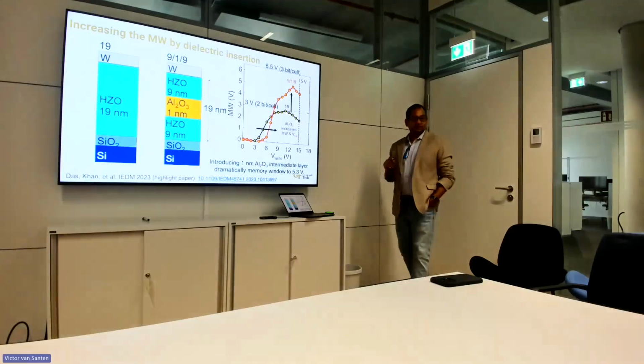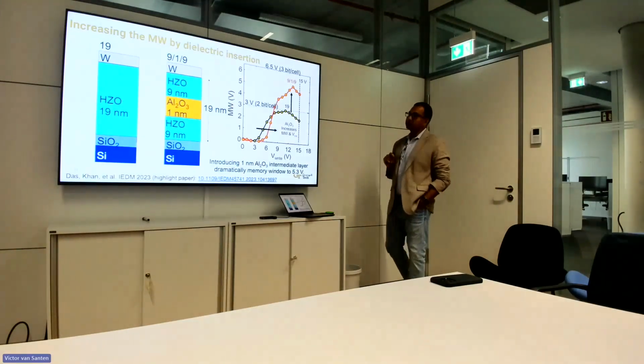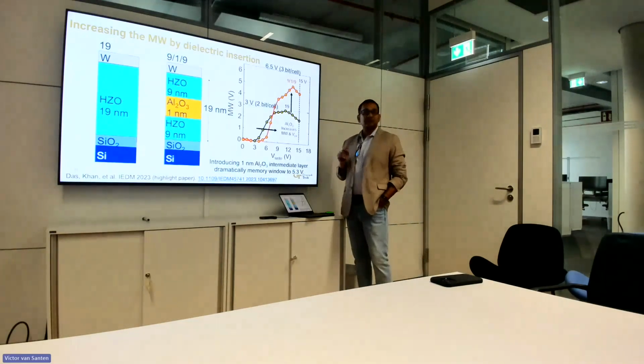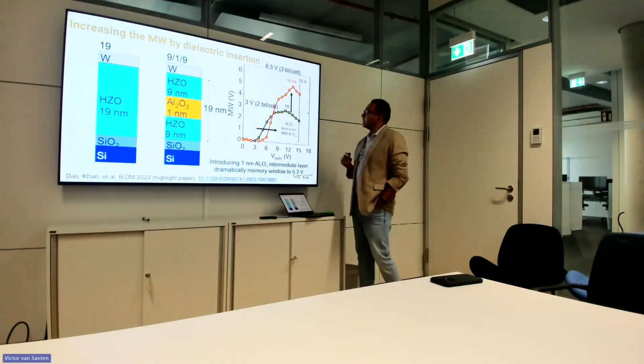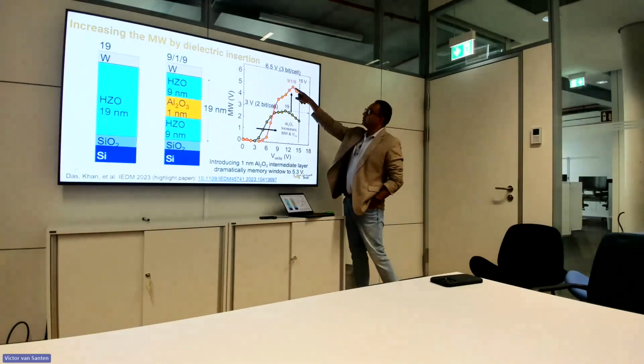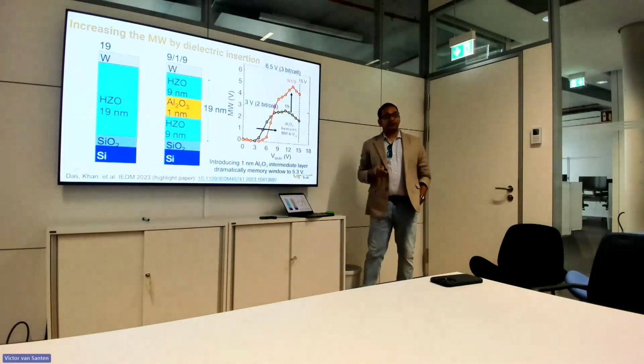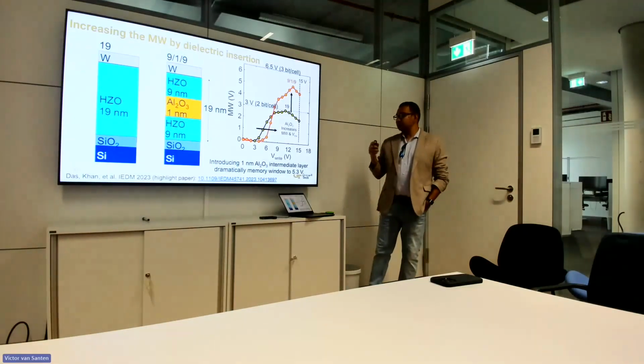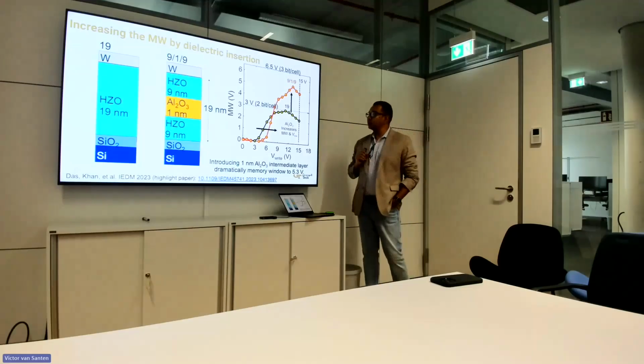So we are very happy that by adding 1 nanometer of aluminum oxide here, we could increase the memory window significantly. Okay, but even then, we are not reaching the 6.5 volt limit. But we already got the idea that if we put an aluminum oxide layer, we can enlarge the memory window significantly.